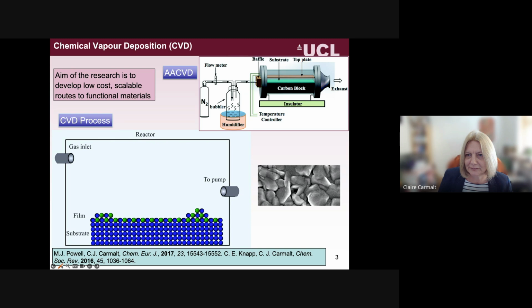So if I could explain the CVD process to you. I do have a little video if I can get it to work. So essentially what you have to do is heat the precursors up into the gas phase, and you get mass transport of the reactants in the gas phase, where the reactions can occur between the chemicals. You then get diffusion of precursors onto your substrate, which is typically heated up. You get absorption of the precursors onto the substrate, followed by surface diffusion, surface reactions to hopefully form the thin film that you want to form, followed by desorption of any byproducts. And those byproducts can then be removed.